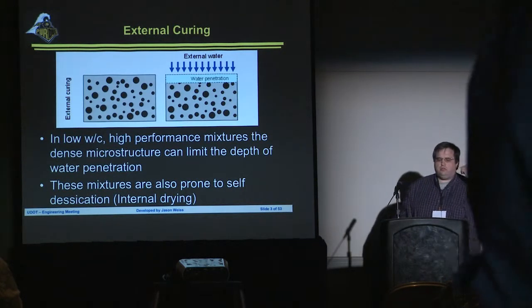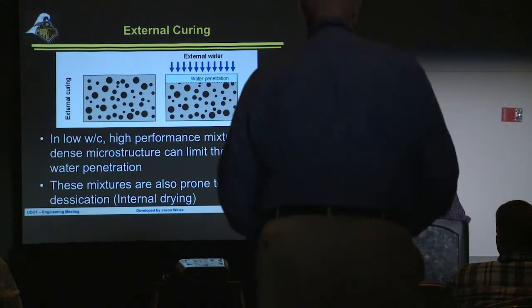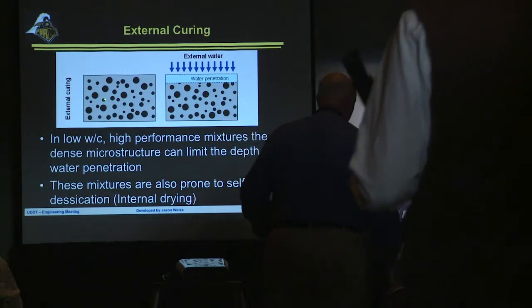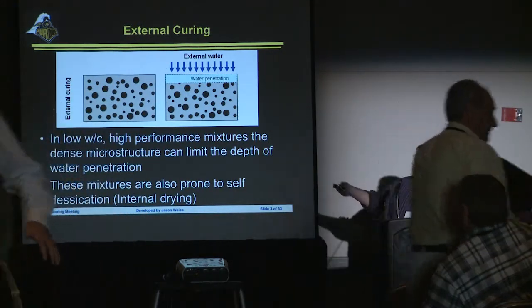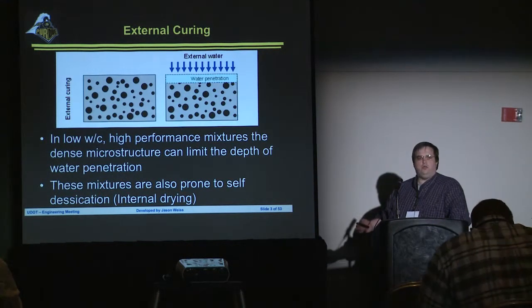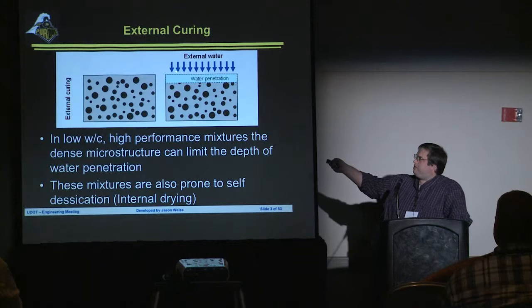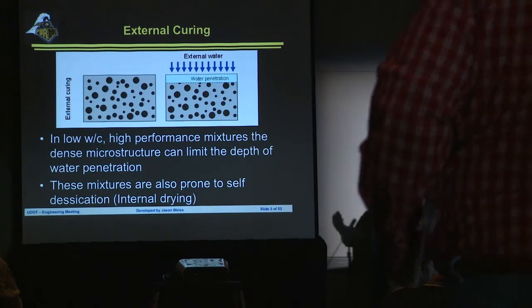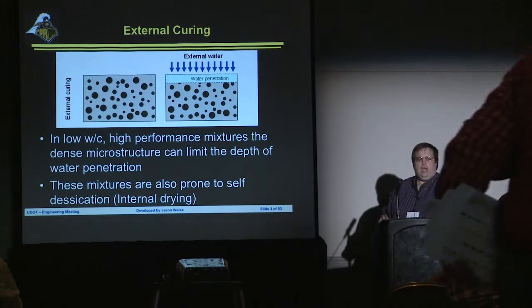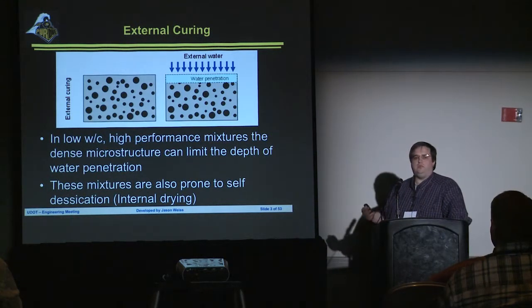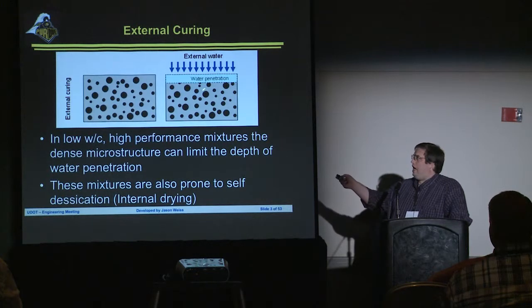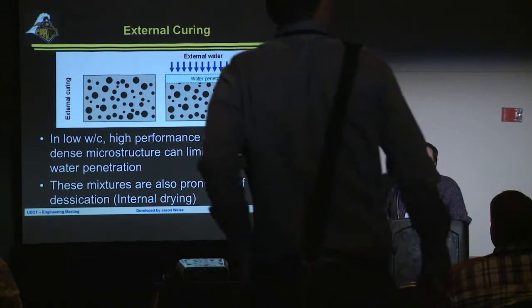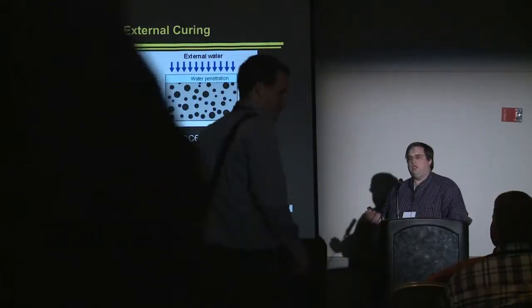Now when I say curing, most of us probably think about the same thing: placing water on top of our concrete. Here we can see a concrete with a pretty low aggregate content, but this is just a conceptual drawing. We've got some aggregates, which are these dark spots, and we've got our matrix, which is this gray stuff. When we apply conventional curing, in the best case scenario we're supplying external water, and that external water sits up on top of the concrete. About 15 or 20 years ago, we had some great debates with people in Canada on how this actually works when you look at high-performance concrete. One of the conclusions coming out was that we just need to make sure we apply good water curing.